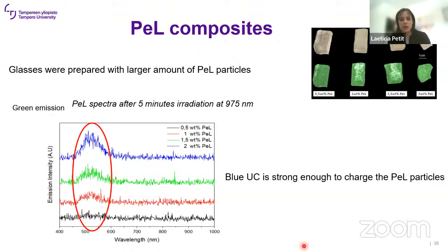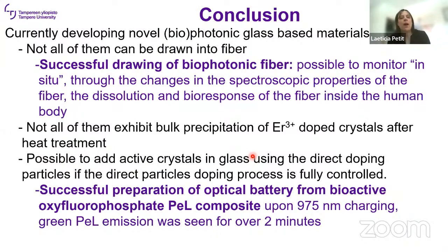So let me conclude. What I tried to show you today is the current research that we do on the development of new photonic glass-based materials. I hope I convinced you that not all of the glasses can be drawn into fibers, but when you tailor the glass composition and the spectroscopic properties, you can actually draw some biophotonic fibers, and you can monitor in situ, through the changes in the spectroscopic properties of the fiber, the dissolution and the bioresponse of the fiber inside the human body. Not all the glasses exhibit this bulk precipitation of rare earth doped crystal after heat treatment.